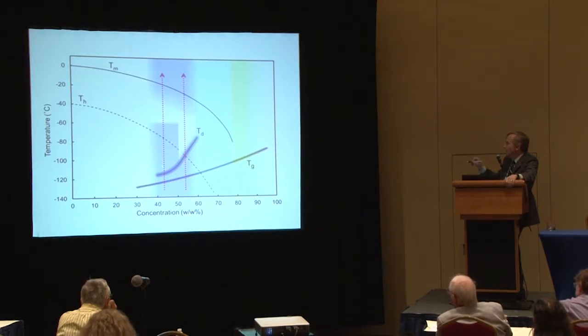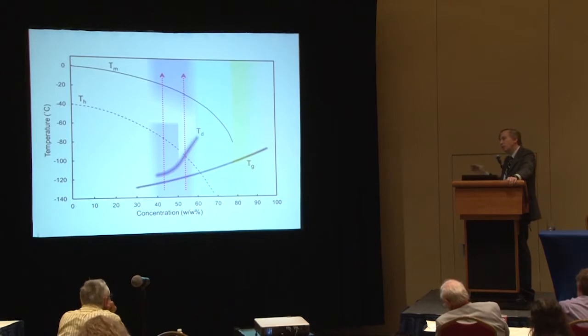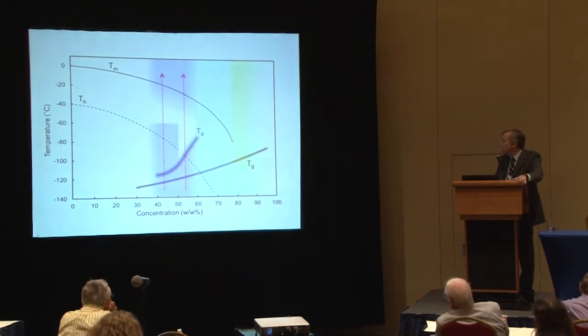Long after the point they devitrified, they'd remain transparent. And then at higher concentrations, you would recover the behavior you'd expect of the solutions becoming opaque immediately upon devitrification. And this was demonstrated for a whole bunch of different cryoprotectant solutes: polyvinyl pyrrolidone, ethylene glycol, propylene glycol, glycerol, and I think even sucrose. So there's some universality of this phenomenon.